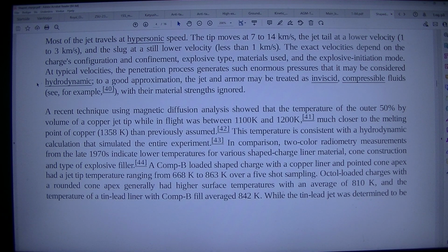The jet tail moves at a lower velocity, 1 to 3 km/s, and the slug at a still lower velocity, less than 1 km/s. The exact velocities depend on the charge's configuration and confinement, explosive type, materials used, and the explosive initiation mode. At typical velocities, the penetration process generates such enormous pressures that it may be considered hydrodynamic.